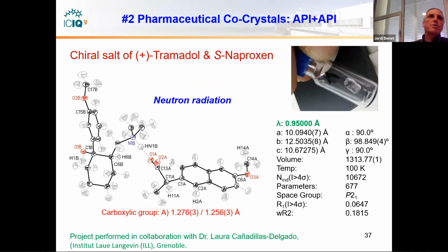We also did a neutron radiation study. In this case, you can see in the image, we have huge crystals, close to the centimeter range, which are needed for making these measurements. We did a project in collaboration with Laura Cañadillas Delgado in Grenoble at the ILL, and so we could measure this same molecule using neutron radiation.